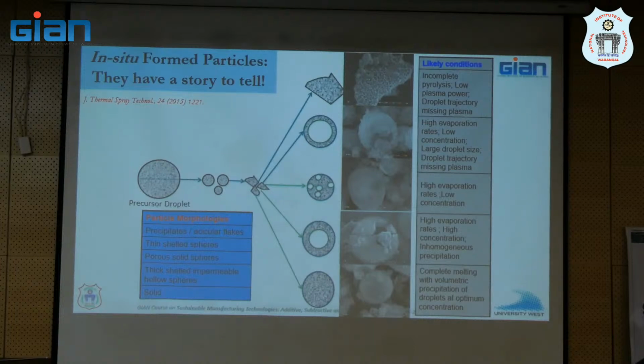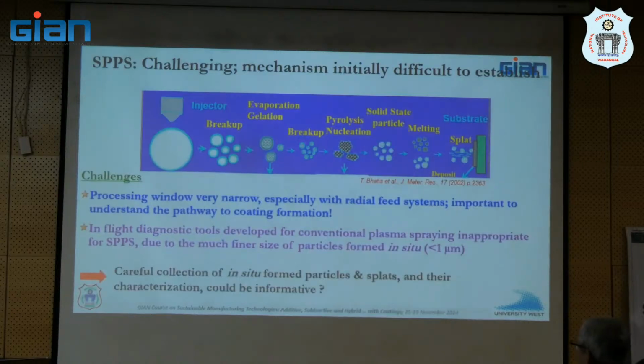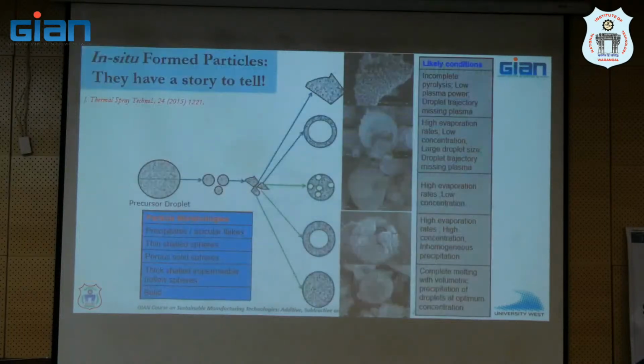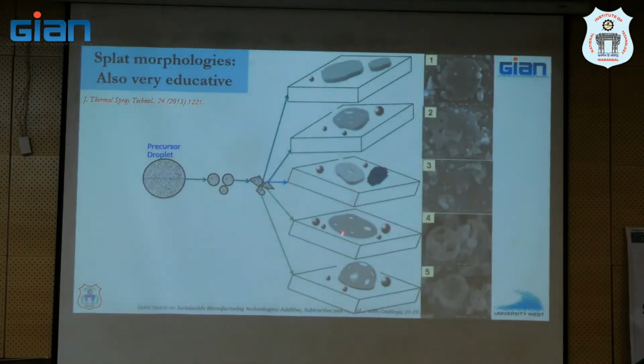While I was at ARCI, this was work by my first PhD student. We have already shown that even though this may be a very complicated looking process, if you do it right, you can actually form in flight these kind of particles, which can then become feedstock for coating. And with some careful process evaluation, we could show that if you don't do it right, you get all lousy stuff. If you do it right, you begin to get these kind of particles, which are a few hundred nanometers, but certainly sub-micron, and that is ideal. That is what you want to see. And similarly, if you don't do it right, you get junk on the substrate, but otherwise, if the stars are aligned and you have prayed hard enough, you get nice pancakes that can lead to formation of coating.